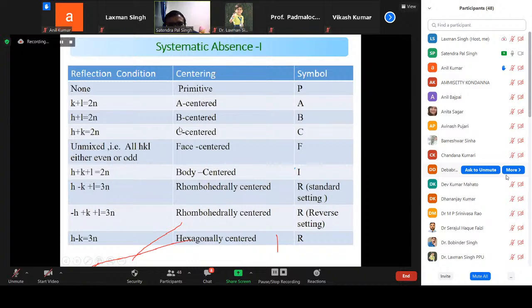If H plus L is even, then we say B-centered. If H plus K is even, then we say C-centered. So based on these systematic absences, we can decide the lattice symbol. We can decide P, A, B, C, F: if HKL are all even or all odd, unmixed, then it will be face-centered. If the sum H plus K plus L is even, then it will be body-centered. If minus H plus K plus L is 3n, then it is rhombohedrally centered in the reverse setting, and if H minus K plus L is 3n, then it is R-centered in the standard setting. And if H minus K is equal to 3n, then it is hexagonally centered. So based on the systematic absences, which are most important, we can decide the lattice symbol: whether it is P, A, B, C, F, I, R, or H.